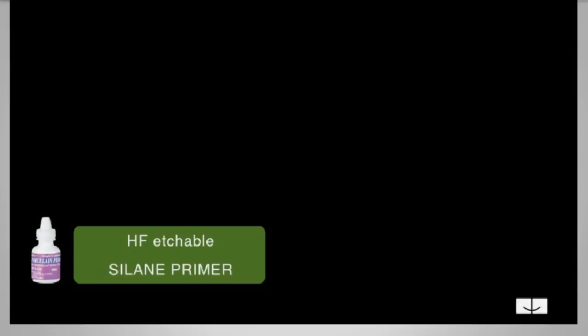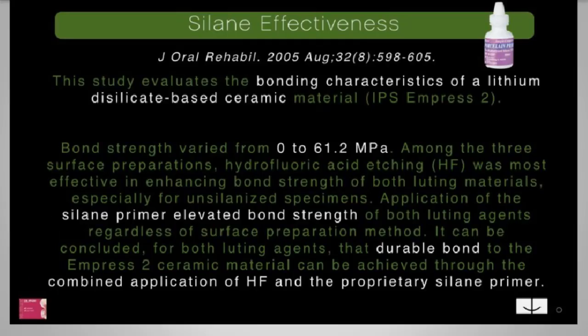So let's talk about the silane first. People ask me, do you really have to use a silane? When it comes to a non-retentive preparation cementation procedure, I always say yes. Use a silane. Here's a study that helps me explain why I use a silane. This one shows a lithium disilicate ceramic, like your Emax. In the test, they did it without silane and with silane, and the bond strength varied all the way from 0 megapascals to 61 megapascals.